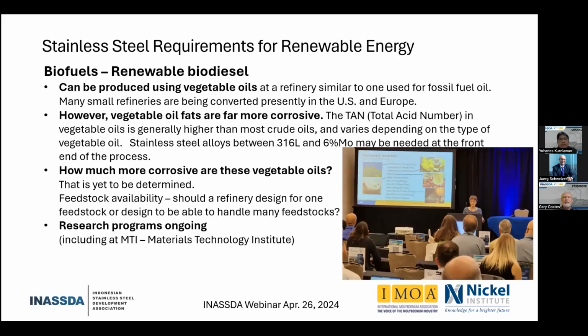So, as I mentioned, a refinery that can produce standard diesel can also do renewable biodiesel. And a lot of small refineries are now being converted in the US and Europe to use vegetable oils. However, it may sound strange, but it was found out that these vegetable oils and fats are far more corrosive than most fossil fuels. Those of you from the petrochemical industry know about the total acid number. It's really an indication of the amount of acid in the oil, and that value is much higher for the vegetable oils. And how high it is depends on the vegetable oil itself.